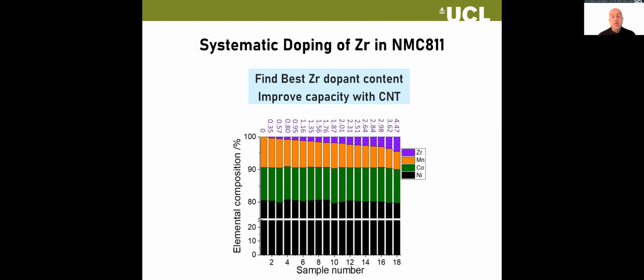What we aimed to do, and in hindsight we probably should have changed the cobalt levels, not the manganese levels, was to replace in an NMC, nickel, manganese, cobalt, with 80% nickel and 10% of both manganese and cobalt. So here's the 100% in terms of element composition. We're replacing about the 10% of manganese with up to about 4% of zirconium in its place, which is these purple bars. This is the actual elemental composition. We had fairly good control of the composition, and these are real values that we obtained.